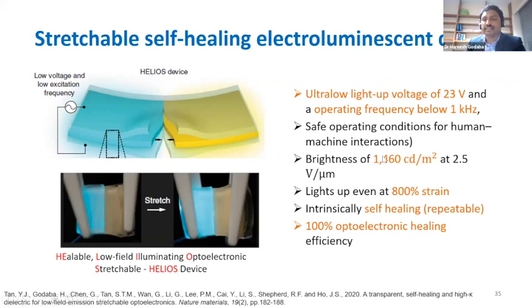The brightness is 1360 candela per meter square. For most mobile phones, if you've got 1000 CD per meter square, this is sufficient for mobile phone displays. And then this can light up even at 800% linear strain. Then the most interesting characteristic is that it is intrinsically self-healing. You cut it and it automatically heals. And optoelectronic healing efficiency, which is the intensity of light that is generated after cutting and healing, is again 100%. So it can recover its full capability of generating luminescence.